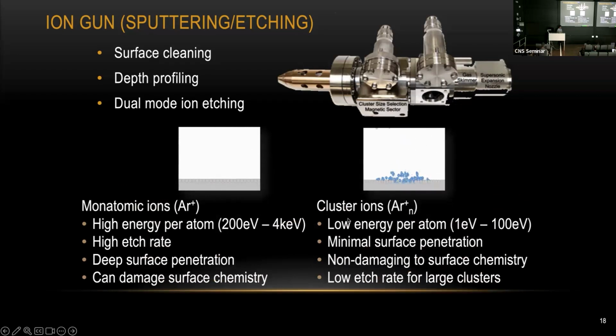So for our machine, we are using argon gas for both cases. So you'll have single monatomic argon ions and cluster ions bombarding your surface. The main difference is that the cluster ion is much more gentle.